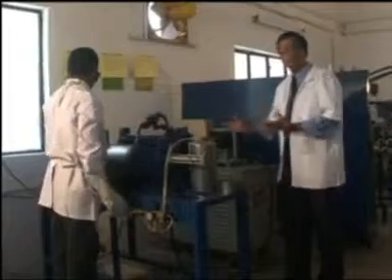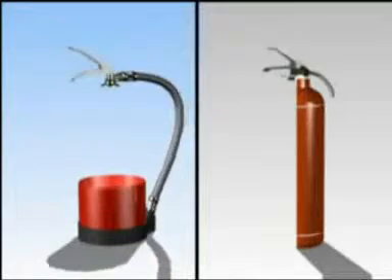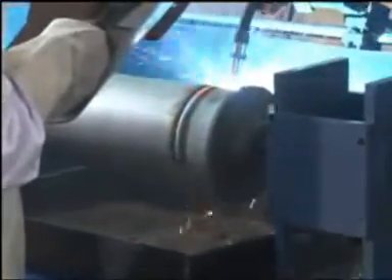Now let's move on to the actual manufacturing and assembly process, beginning with the container. The container's strength is obviously affected by the amount of welding on the surface — more welded seams means more chance of leaking. In the mid-90s, ceasefire pioneered the deep drawn process, where large steel sheets are preformed into shape using hydraulic presses, requiring no vertical welding at all. So in this 5 kg container, for instance, the potential leakage area is reduced by up to 57%. For the remaining small horizontal seams at the top and base, we use a mixed CO2 welding process — 100% automated, with motorized fixtures holding the container in place as an electronically guided torch performs a precise welding job. Contrast this with the industry norm of manual welding, obviously more prone to crack and leak.